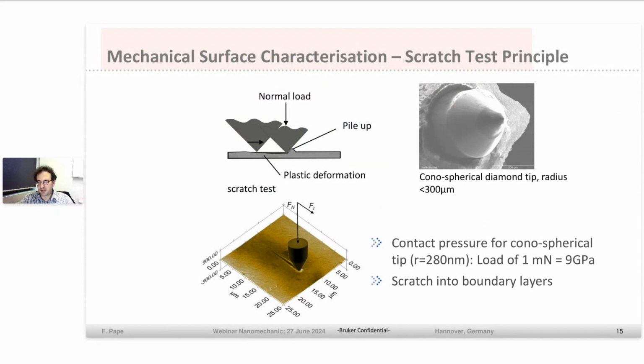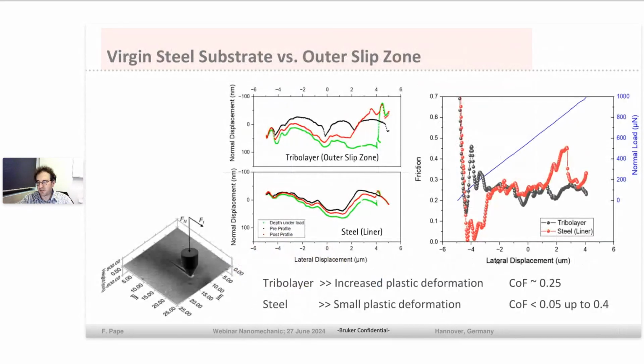So the principle is shown here. For this, we used a conospherical diamond cone tip, and we scratched along the surface with increasing normal load, and we can measure the pileup aside and also the plastic and elastic deformation. Doing so, we measured in 3 steps that we can see here.